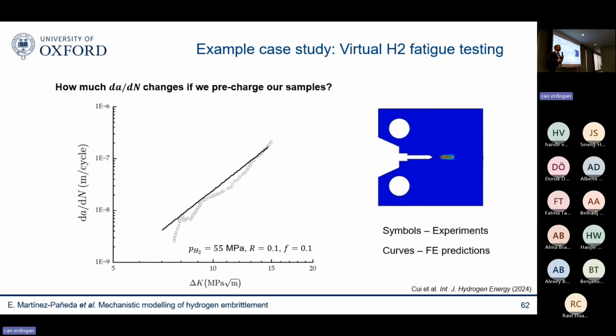And now we use the model to try to understand things. One of the problems with these experiments is that because they're expensive and they take time, they do not expose the sample to hydrogen and then do the mechanical test. They do both at the same time. And this is a problem because in practical applications, pressure vessels, pipelines, they're going to be exposed to hydrogen for a long time. So we can do that easily in our model.